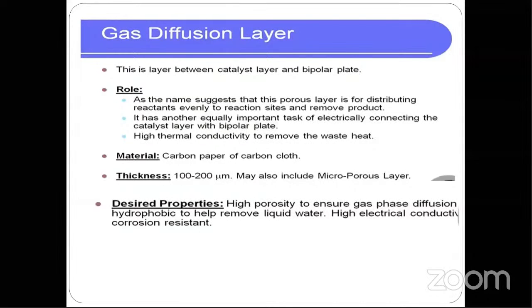So materials we have are like carbon paper or carbon cloth and other materials. The thickness here is a little bit thicker than your catalyst layer, around 100 to 200 microns. If you see the desired properties, basically it should have high porosity to ensure gas phase diffusion, and it should be hydrophobic to help remove the liquid water, because if this liquid water is staying there, it will stop these reactants from flowing to the cell. Basically, it will clog without supplying the hydrogen as well as oxygen. Then your fuel cell function will stop. And also it should have high electrical conductivity and corrosion resistance.